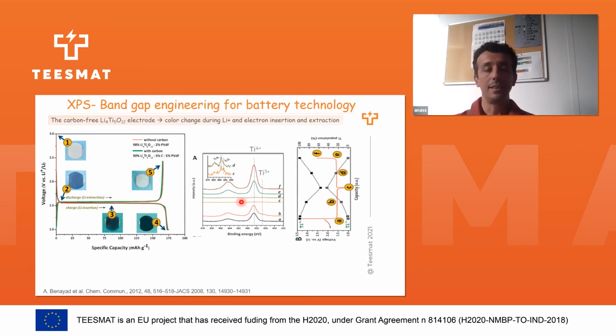How can we explain this? I didn't say before that the XPS analysis depth is 5 nanometers. That means we do not see titanium anymore because it's buried beneath some thick layer, at least 5 nanometers thick. But when we zoom in on this area, we can still see some titanium. What does that mean? That we formed some SEI at the surface of the material with a thickness of at least 5 nanometers. But what is interesting is that when we charge, the titanium appears again, which means that this SEI was dissolved. That's why for many years, LTO was considered SEI-free, but in fact, the SEI is formed during discharge and is dissolved during charge. Just when we do post-mortem, sometimes we do not observe this phenomenon.